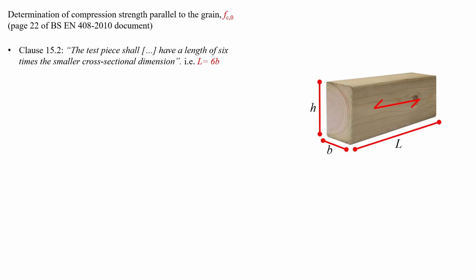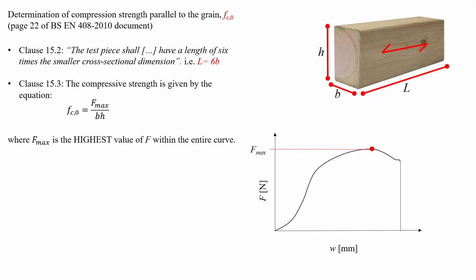Right. So our sample length should be 6 times the breadth, and the height for this test should be the same as the breadth. Okay. And what we're going to get is a compressive strength given by this equation.